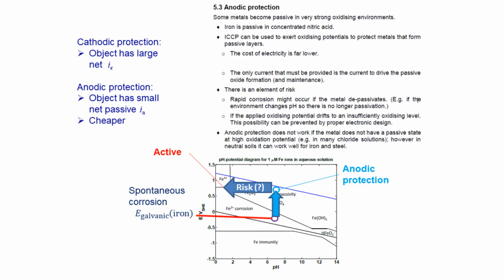Anodic protection looks at this aspect of the pH potential diagram, that is, for iron and some of the other transition metals, the fact that they have a higher solid oxide which provides passivity in highly oxidizing environments, and it says that we can exploit this using a powered corrosion protection system. If we apply not a more cathodic potential, which we did previously, but if we actually deliberately apply a moderately strong oxidizing potential to the surface of the iron.